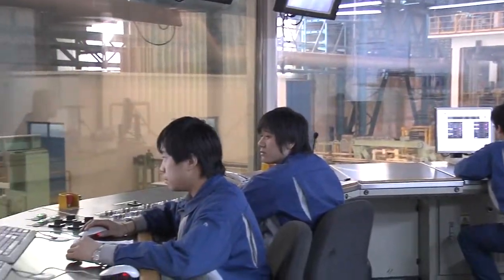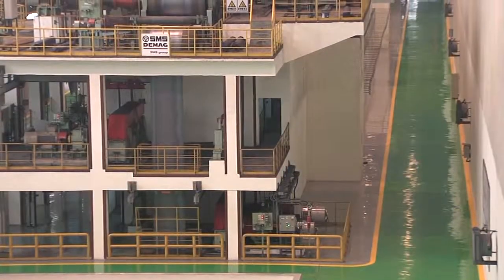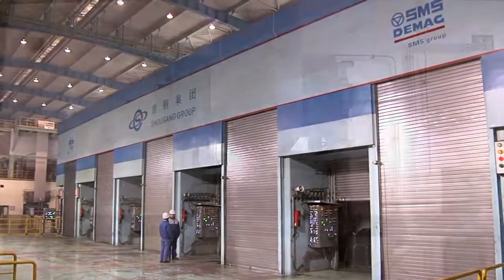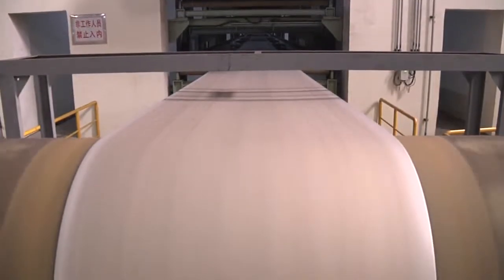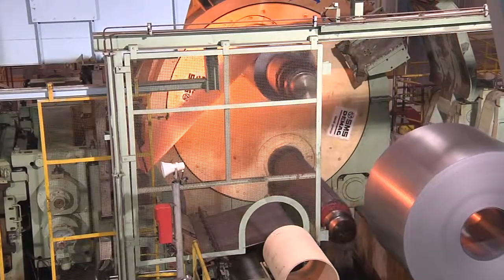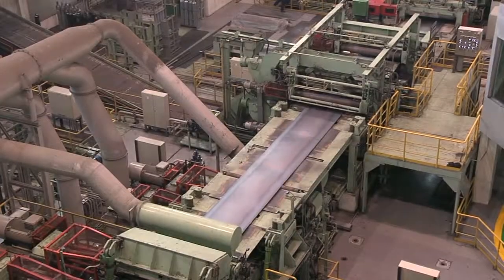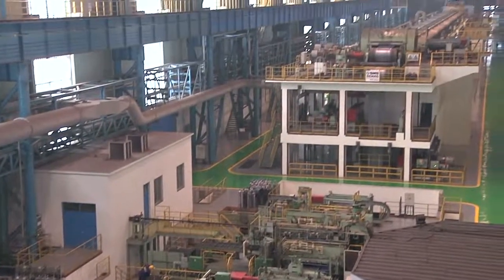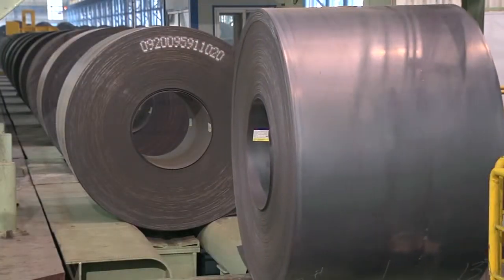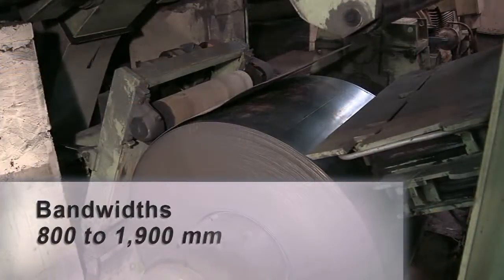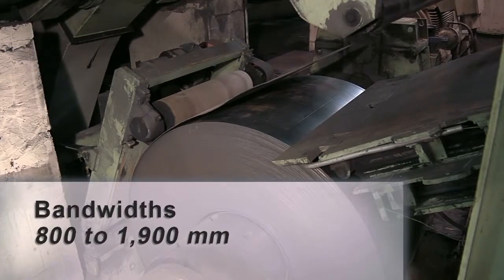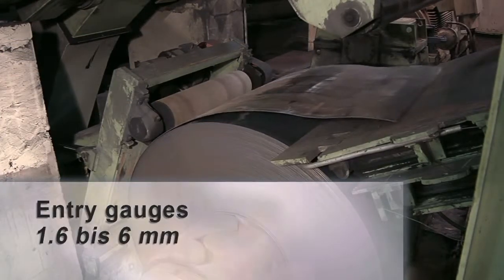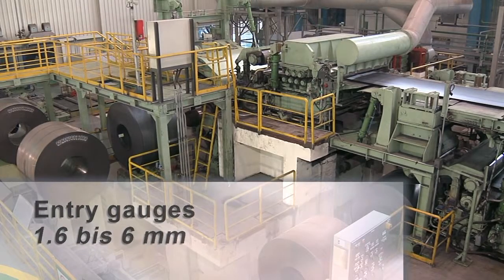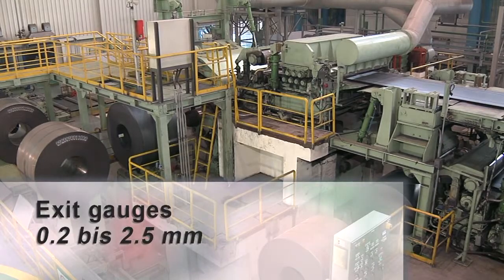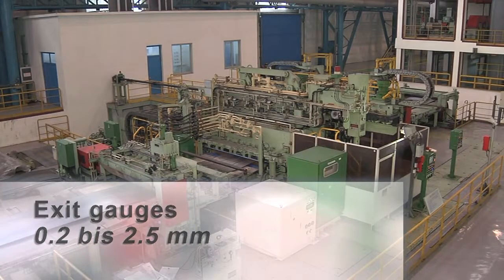The facilities upstream of the annealing line are also from SMS Siemag. There is a turbulence pickling line coupled with a tandem cold mill. It processes hot wide strip, which is also produced on an SMS facility. The pickling section starts with a payoff group with 2 reels. The strips are 800 to 1,900 millimeters wide. The entry gauges are in the range of 1.6 to 6 millimeters. And it is possible to produce strips with final gauges of 0.2 to 2.5 millimeters.